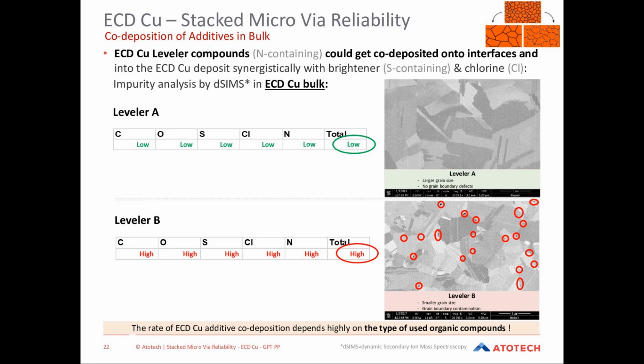And analyzing by dSIMS now the purity of this copper deposit, you see we find for all elements which are of interest in this regard, very, very low concentrations of all these elements in this bulk of this electroplated copper deposit, where we have used the leveler A. At the bottom of the page, you see another example of another copper plating process using a different leveler type, leveler B. And here you already see that the crystal structure is not so regular. It is more disturbed. You see increased twinning in the crystals, which is not basically bad, but shows already you have more stress in this copper deposit.